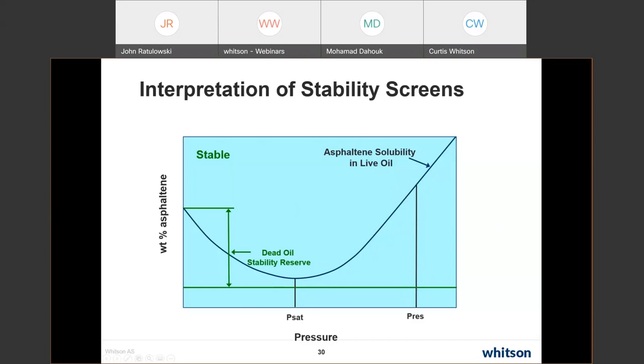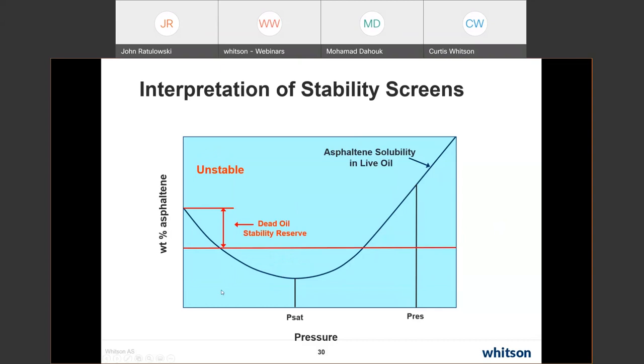However, if I have a low dead oil stability reserve, then I am going to have a large region of pressure where I see destabilization. And so that's where these rules of thumb come in when people do the dead oil stability reserve or the compositional data. They'll have a bunch of fields and they'll look and say, when I have this small amount of stability reserve, oftentimes I have a problem. But you still have to look at the other side. I may have a low stability reserve, but if I'm sitting at saturation pressure, I still don't have a problem. So you really need to look at these two screens together. And that probably took longer than what it needed to take, but it's one of my kind of pet peeves on the use of screens, that people don't use them properly.